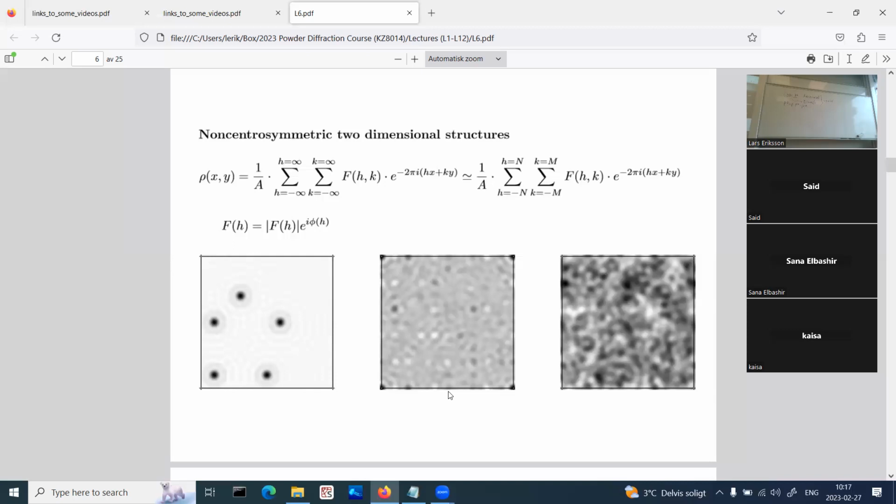So when they flattened or reversed the sign, and then one can calculate the diffraction pattern and use the known amplitudes to reconstruct it, and you still get crap. But use this, let the computer do it, because they don't have to work. And after 200 times, something like that, suddenly the true structure appears. That works some of the time. This is known nowadays as charge flipping.